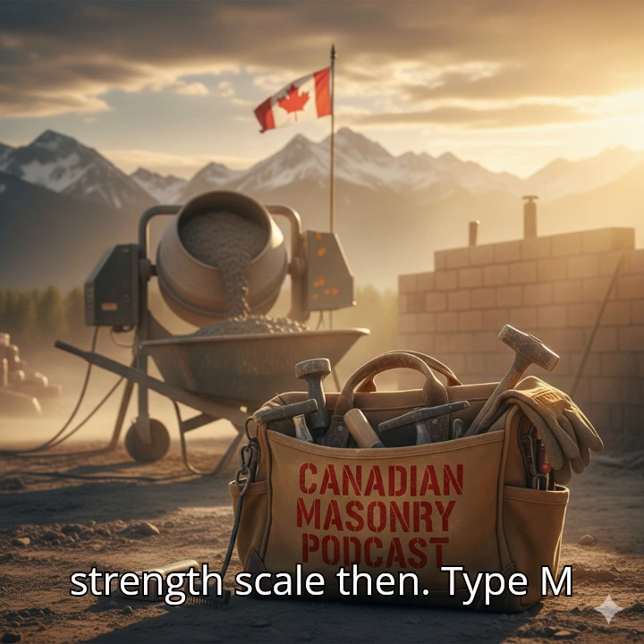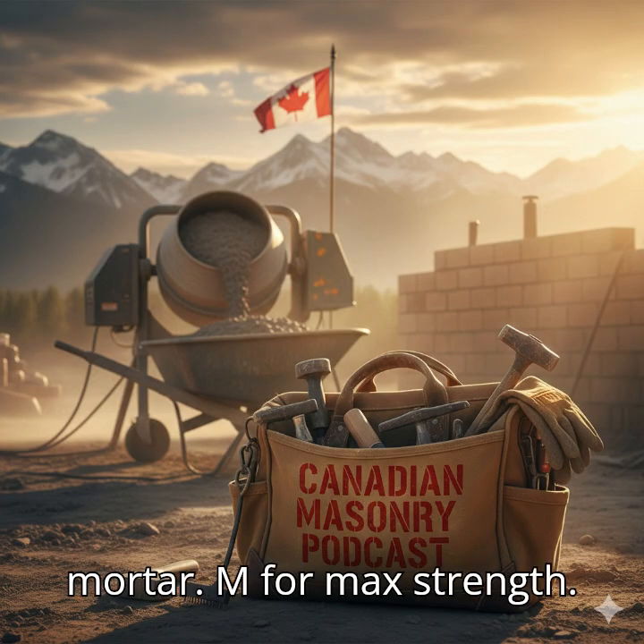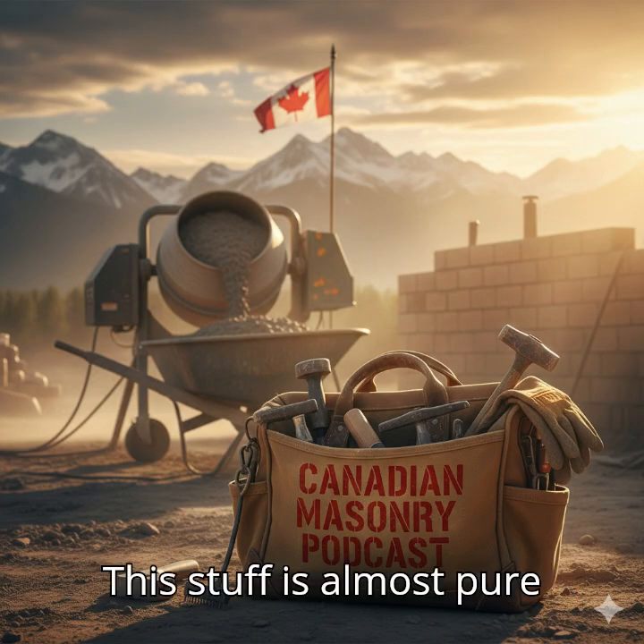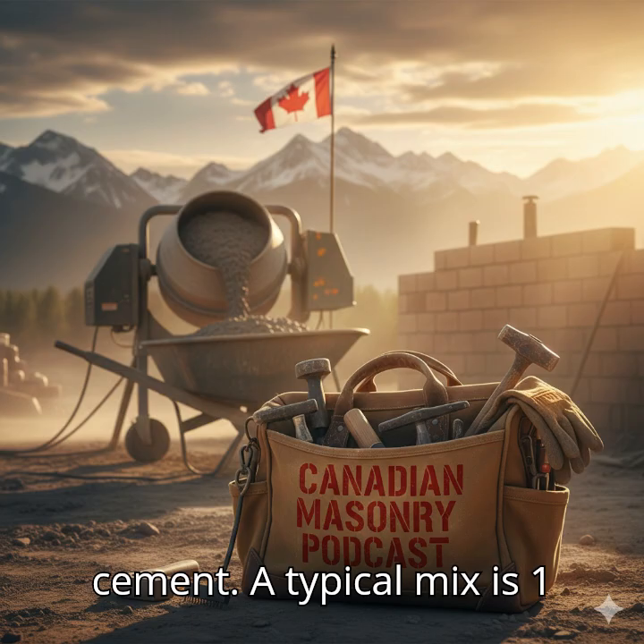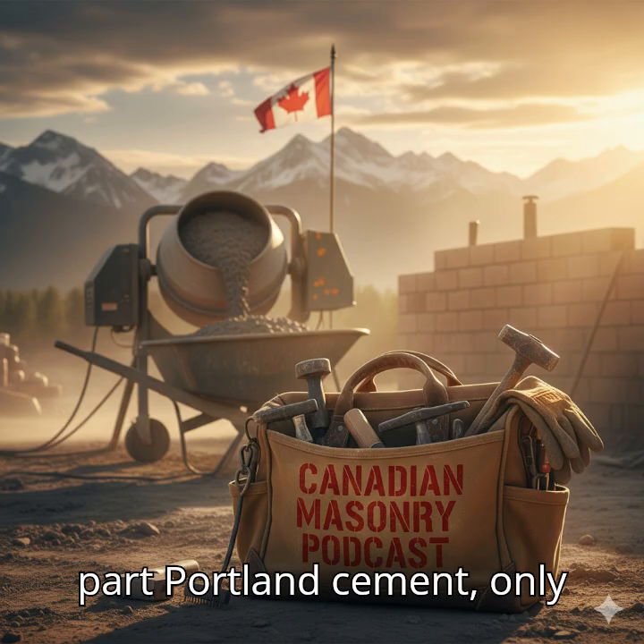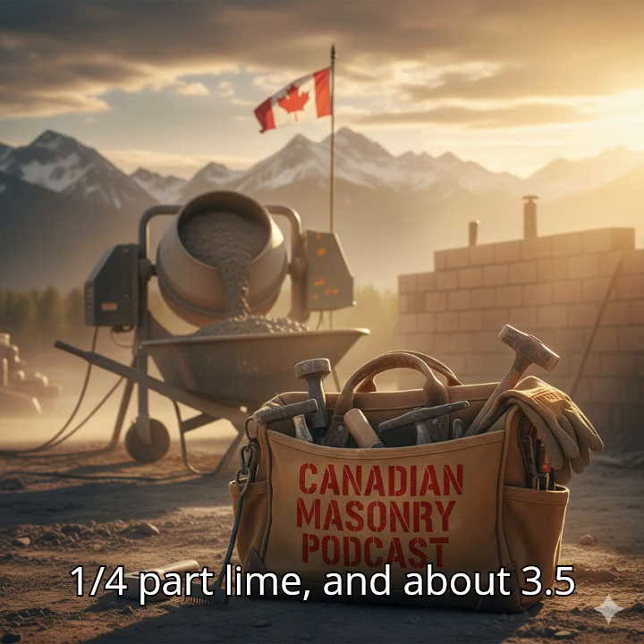Let's start at the top of the strength scale then. Type M mortar. M for max strength. This stuff is almost pure cement. A typical mix is 1 part Portland cement, only 1/4 part lime, and about 3.5 parts sand.